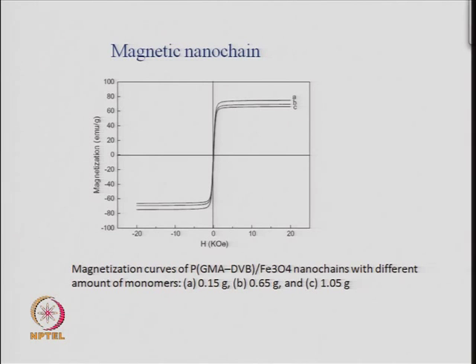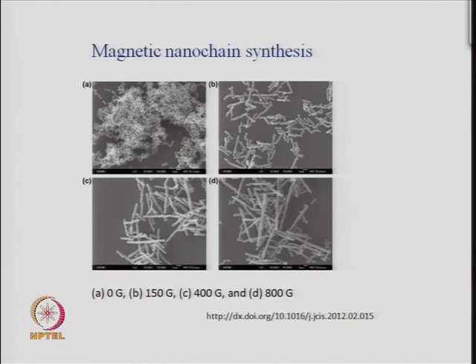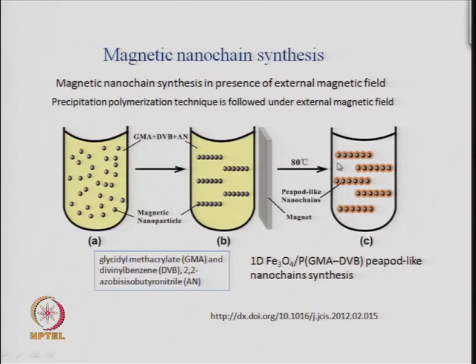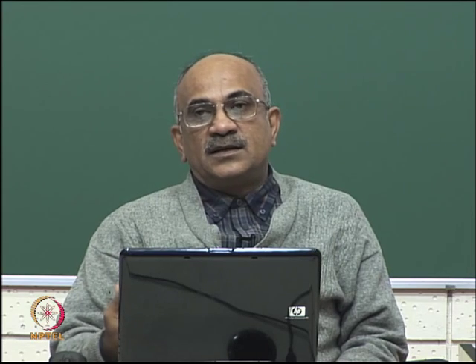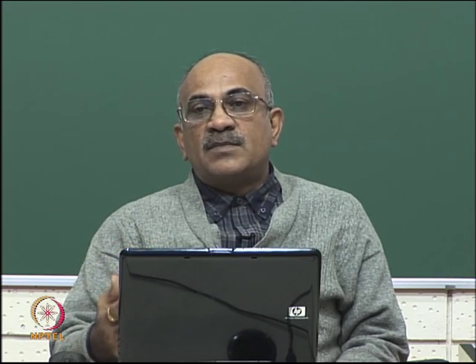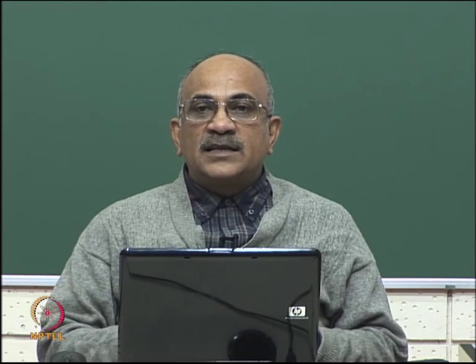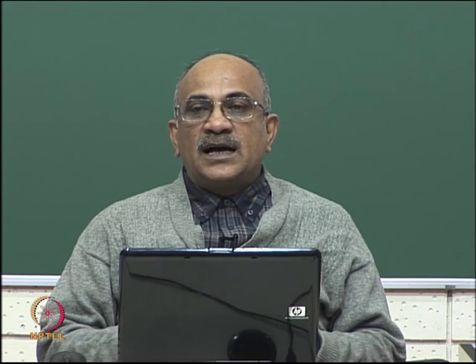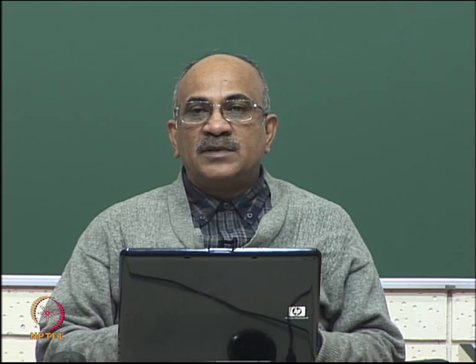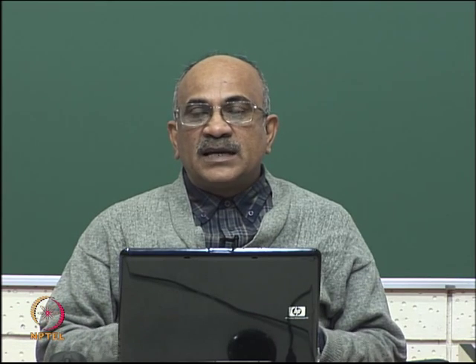Now, if you measure the property of these chains, depending on different amounts of monomers, because you want to polymerize on top of this, you want this polymer. So, if you add different amounts of monomers, the amount of polymerization will be different, and so the magnetization will also be different, because if it is uncovered, you will see some magnetization. If you cover it with a polymer, then the effect of magnetization will decrease. So, that one can study when you do the real experiment of measuring the magnetization using either a VSM, which is a vibrating sample magnetometer, or a SQUID, where you can measure magnetization.